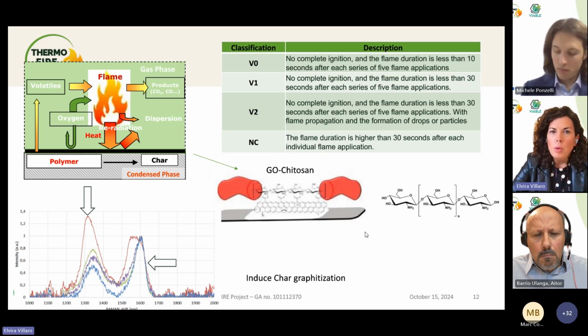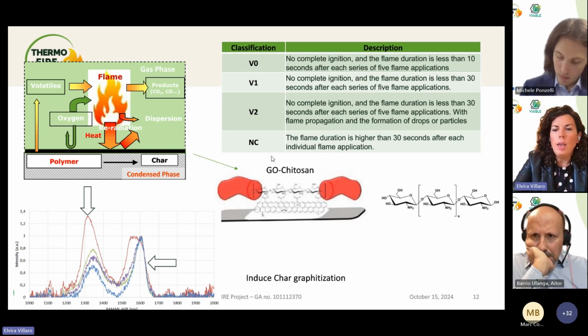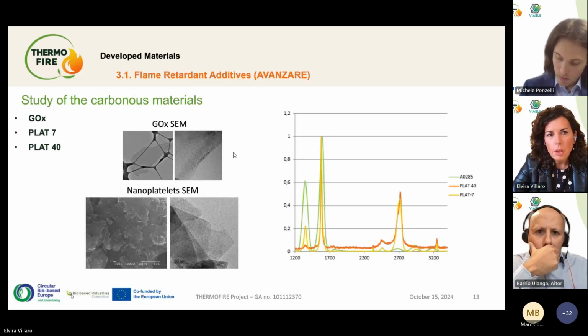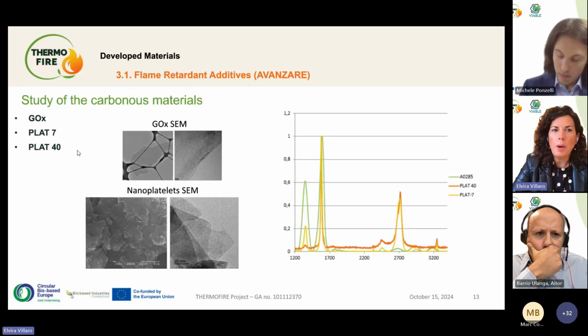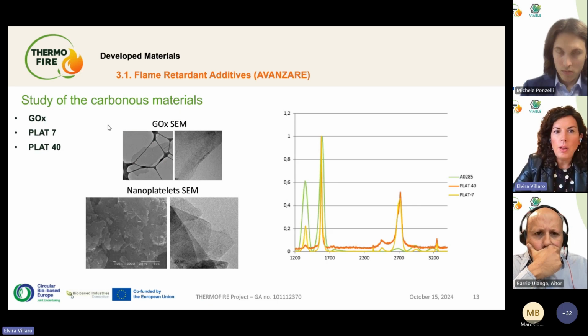Until the moment, what we are doing is testing these additives in polyamide 11, and we are testing according to the UL94. We can see here the basic classification according to the afterglowing time and the combustion time. So the materials that we are combining with the bio-based polymer are some of this graphene oxide and also the nanoplatelets.